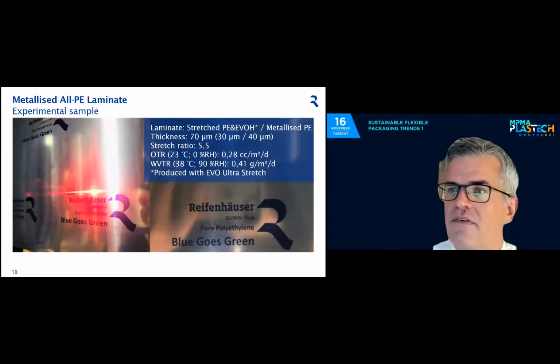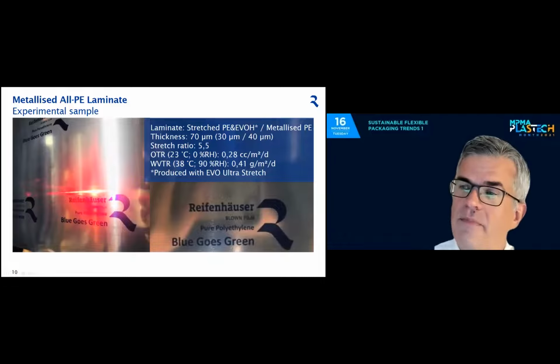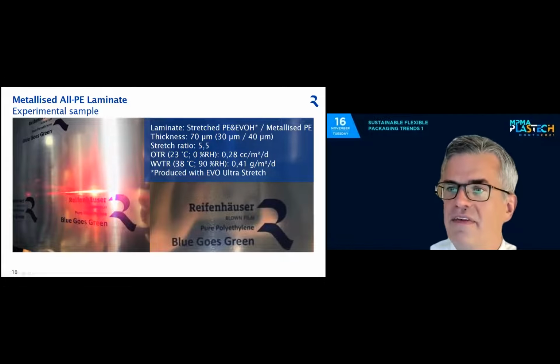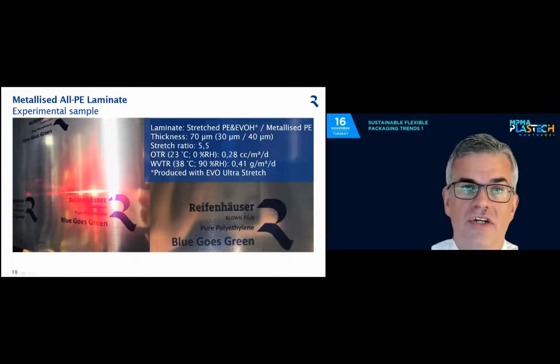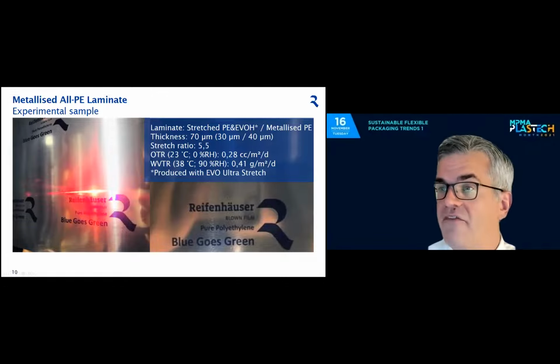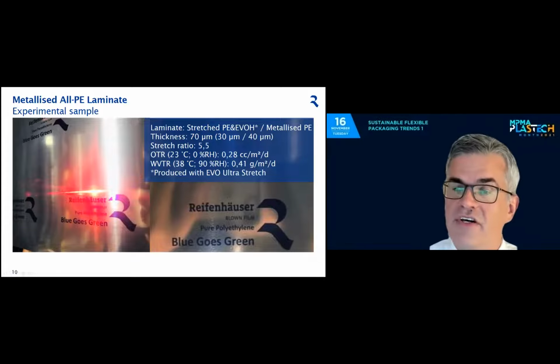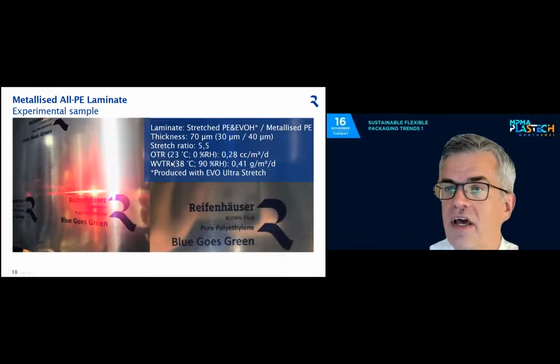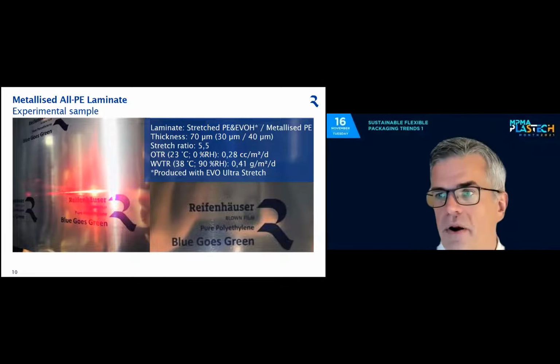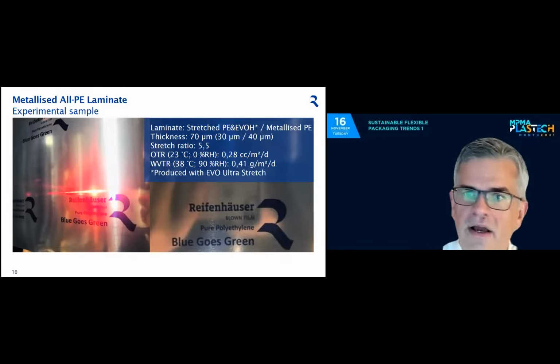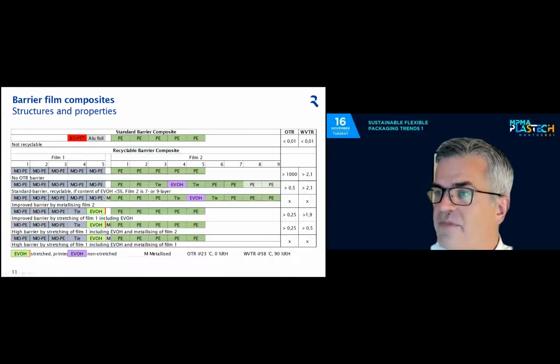metallize the PE film. So again, we have a stretched 5-layer film, PE and EVOH, like we had in the example before. But we took the PE lamination film, which was a very simple film, 3 layers only, and we metallized it. We came up with a total thickness, in this case, of 70 micron, again 30 micron for the stretch laminate made of PE and EVOH, and the metallized PE film was like 40 microns, stretch ratio 5.5 for the PE EVOH 5-layer film. And then we end up with oxygen and water vapor transmission rates for both well below 1, giving some nice barrier properties.